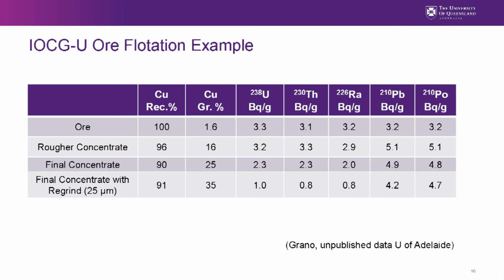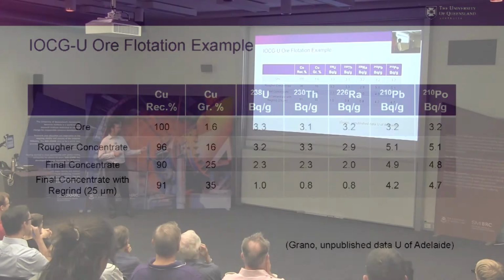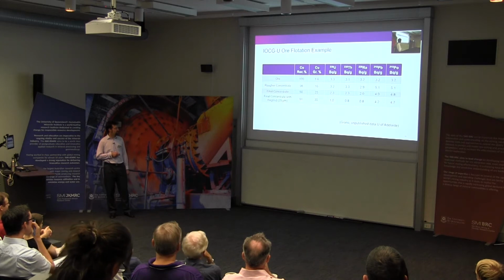And then in a final concentrate step, the copper recovery dropped off a bit, the grade went up substantially, and the radionuclides were cut back a little bit, but especially the uranium, thorium, and radium. But the lead and the polonium weren't cut back quite as much. And then with the second sample, there was a regrind done to 25 microns, and in this case, the uranium, thorium, and radium were cut back quite substantially by doing that regrind. But if you look at the lead and the polonium, it's kind of remained high.